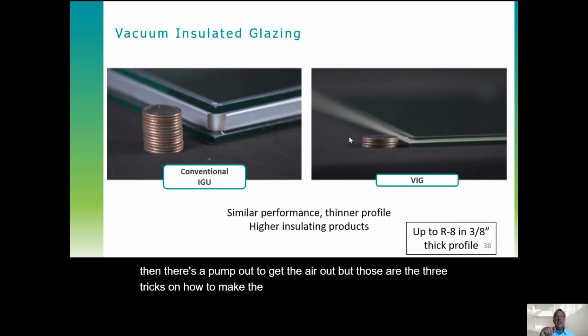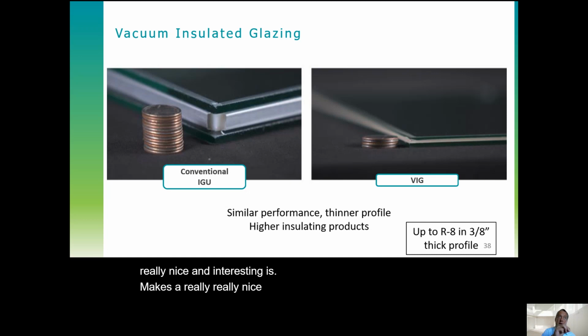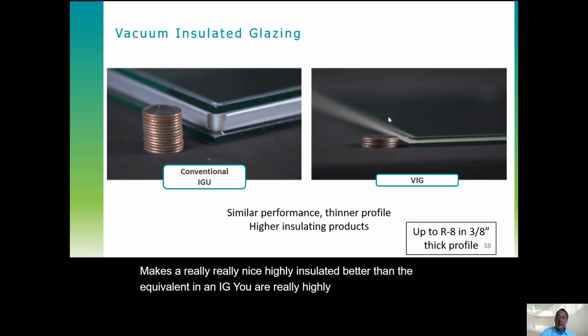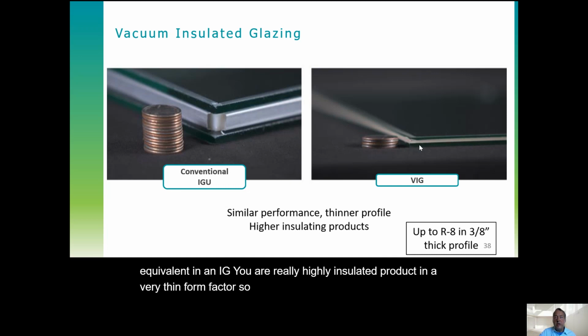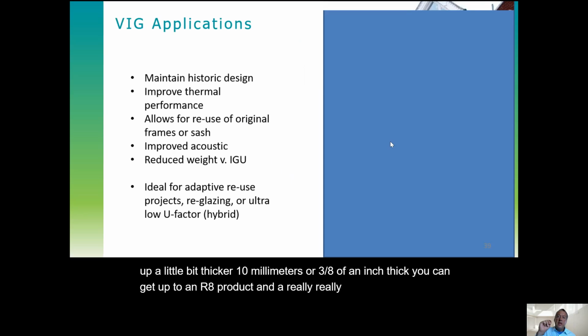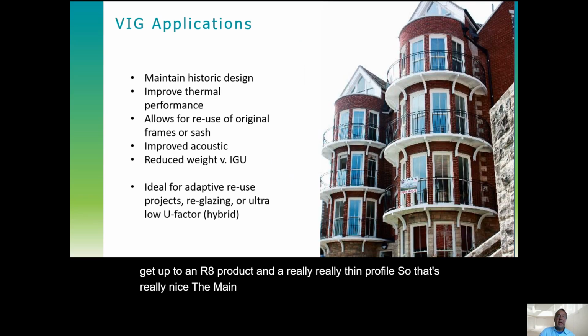But the reason this is really nice and interesting is it makes a really, really nice, highly insulated, better than the equivalent in an IGU, a really highly insulated product in a very thin form factor. So in 6 millimeters and a 1/4 inch thick, you can get down to about a 0.18 or an R5 insulator. And if you go up a little bit thicker, 10 millimeters or 3/8 of an inch thick, you can get up to an R8 product in a really, really thin profile. So that's really nice.